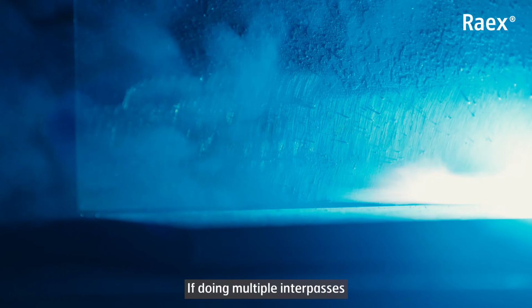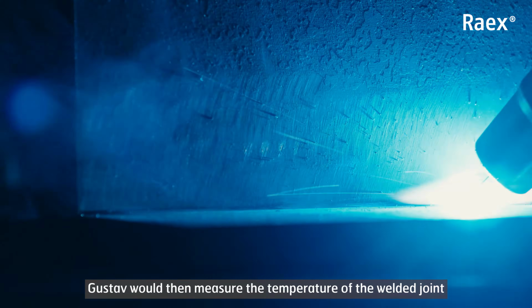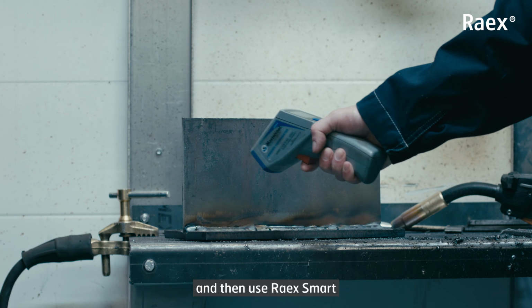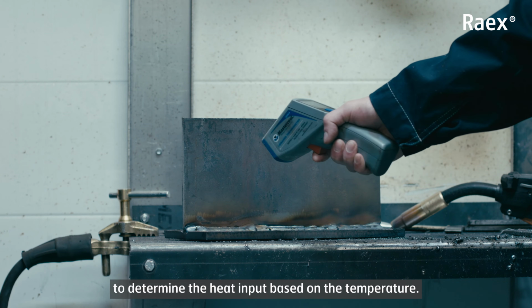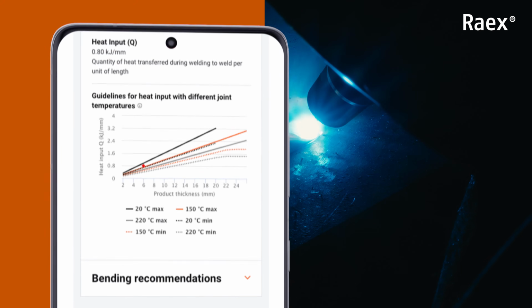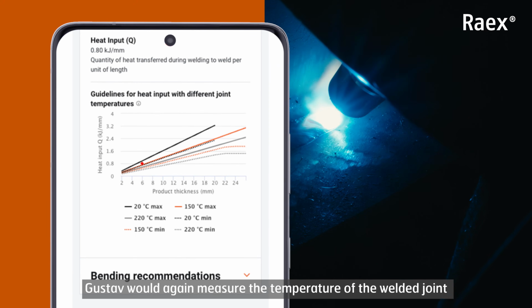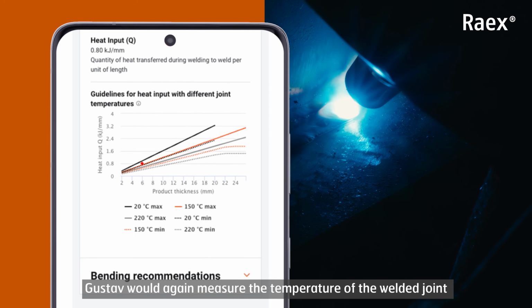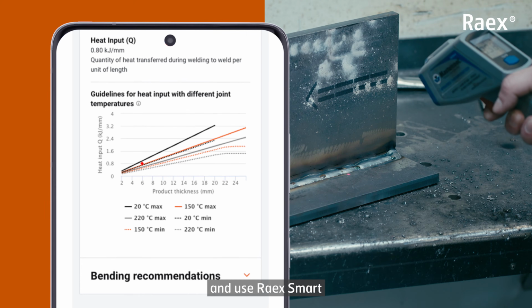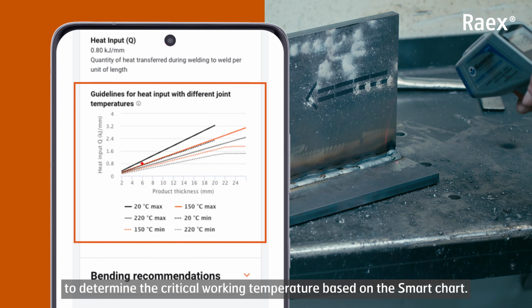If doing multiple interpasses, Gustav would then measure the temperature of the welded joint and then use Raex Smart to determine the heat input based on the temperature. For the third interpass, Gustav would again measure the temperature of the welded joint and use Raex Smart to determine the critical working temperature based on the Smart chart.